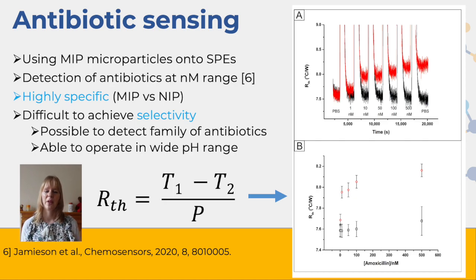Now here we worked with a molecularly imprinted polymer for amoxicillin, but we also work with a non-imprinted polymer, which serves as a reference. A non-imprinted polymer is produced in almost exactly the same way as a molecularly imprinted polymer. What you do is, rather than having your target in the beginning, you just follow exactly the same polymerization process, but without the presence of the target. So in terms of chemical composition, what you get is exactly the same. However, this will not be a porous material that will contain a cavity of binding sites. So all of the binding that you see to your non-imprinted polymer is all non-specific. Similarly, you could also imprint with another target, and that would allow you to test your cross-reactivity.